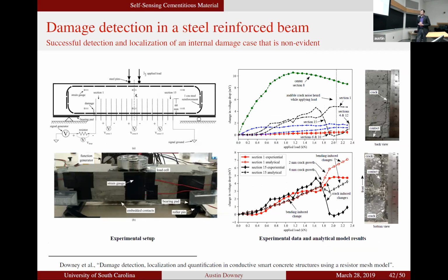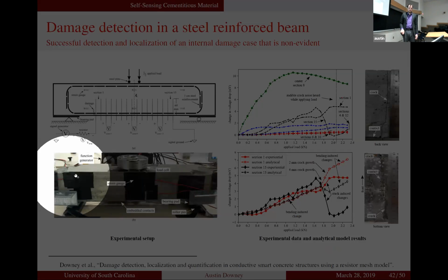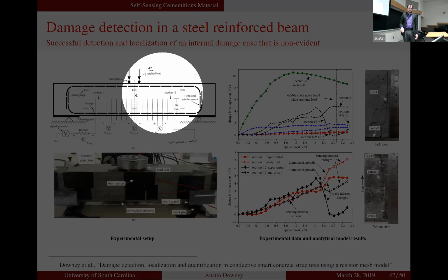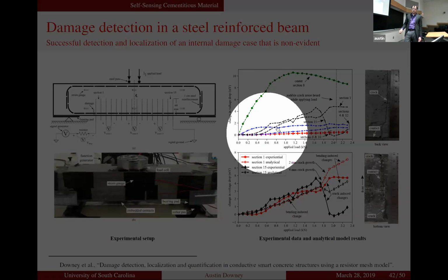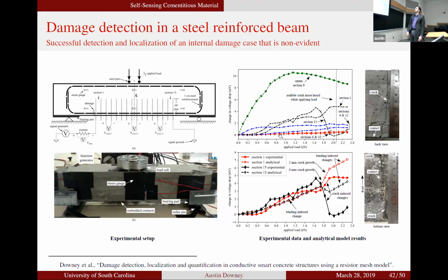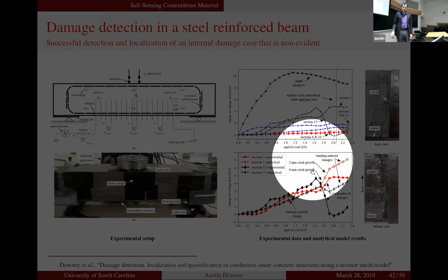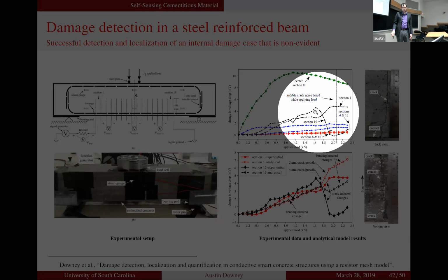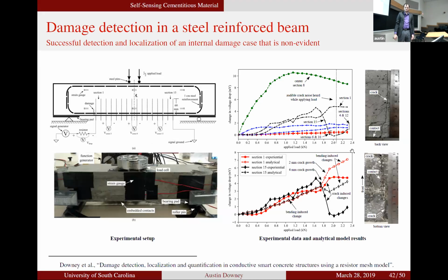But then we wanted a much larger beam. And so here we have a much larger beam. And this whole beam is filled with multi-walled carbon nanotubes. And it's simply supported. And then we're going to apply a load down the center. And what we get is we can track the strain throughout the beam at different sections. We can track that quite well. And then at an applied load of about 1.7 kilonewtons here, we have an audible crack that forms in the beam, right? And so this drop here is a function of that crack opening.